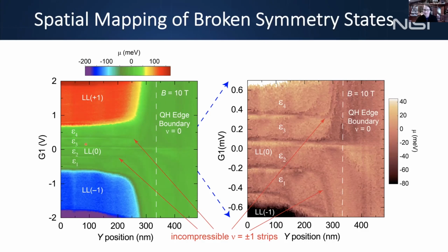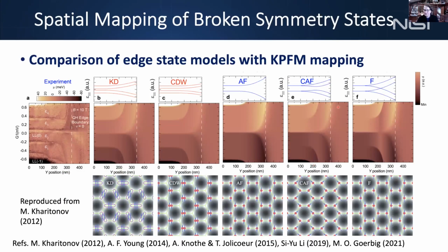If we go a little higher in magnetic field, we can see better the broken symmetry states inside the n equals 0 Landau level. So here you have the 4 sublevels. These are those excursions that you saw before. If I blow that up, you can see that here. So here you see the hole states, the negative Landau levels going down, positive ones going up. But we can also follow the plus or minus 1 Landau incompressible strips here. This one goes up, this one goes down. And then we can compare that with what we'd expect from these different ground state symmetries.